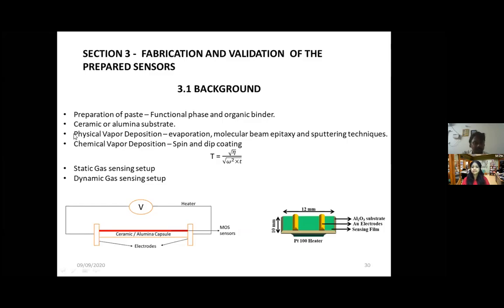The fabrication can be done either by physical vapor deposition or chemical vapor deposition. Physical vapor deposition consists of evaporation, molecular beam epitaxy, and sputtering techniques. We use chemical vapor deposition. The difficulty we faced in physical vapor deposition is that we don't have exact control over what is happening inside the instrument, and moreover we cannot optimize many of the parameters, and it requires a trained technician and dedicated space and all those things. So we go for chemical vapor deposition, with spin and dip coating.